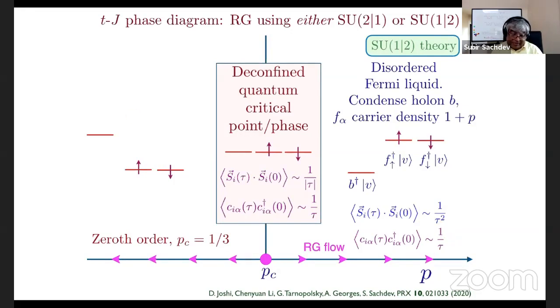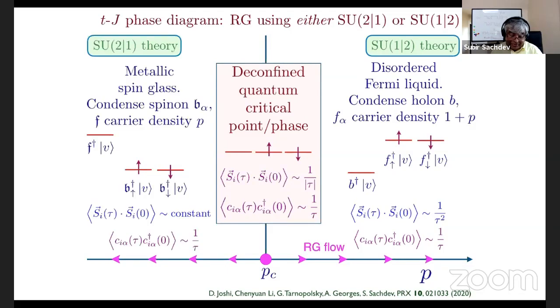Okay, but what about on this side? Well, on this side, by this logic, now these states are becoming very low in energy. So it's always preferable to make the low energy guys a boson. So you make this the boson and that the fermion. Now the boson carries spin. This is the SU(2|1) theory. So when these bosons condense, you're going to get a spin glass state, which is in fact what we saw already happened at P equals 0, very weak spin glass order. So the spin correlation decays at long time to a constant.